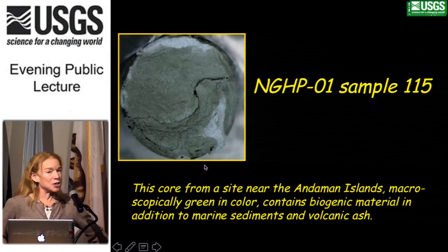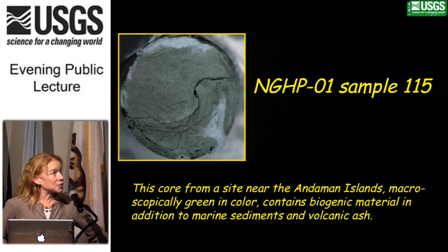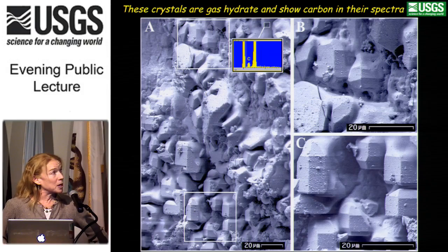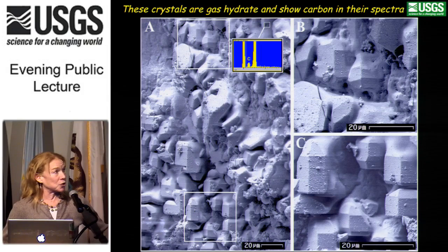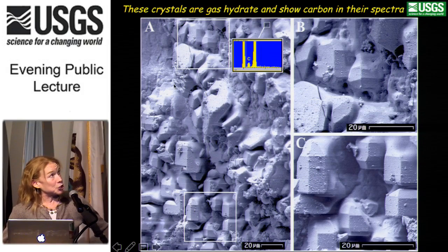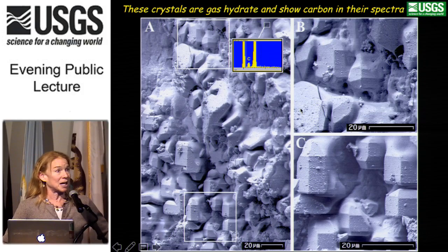I mentioned we're also interested in the sediments that often form with the hydrates or around the sediments. I'm going to use this one core to finish up here. This core also had some beautiful crystals along part of it in some open cavities. These two boxes here are enlarged at the right where you can get a better view of the crystals. Very often it's hard to distinguish, or we want to make sure that we're actually looking at hydrate and not ice. So we use EDS, and it either shows the carbon signal or it doesn't.